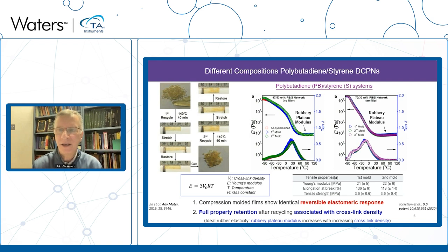And in the rubbery plateau region, the value of the modulus or the stiffness is actually proportional to the cross-link density. We know that this is work that was actually established decades ago by Flory in his ideal rubber elasticity theory. And so we're simply measuring the rubbery plateau modulus in these cases. You see, as a function of as-synthesized and molding and remolding, with an experimental error, we end up getting a very good recovery of the modulus, meaning that we get very good recovery of cross-link density after reprocessing.